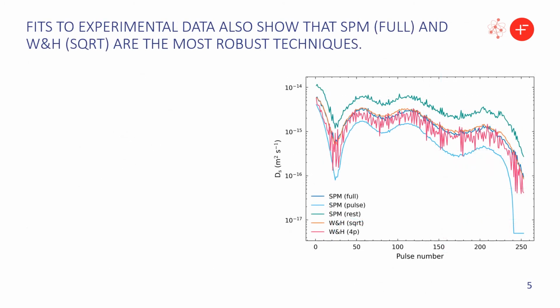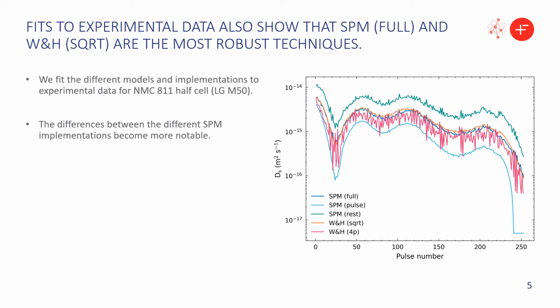So that was the synthetic data, but of course, we want to compare it with experimental data as well. And what we do here is fit the models and the different implementations to experimental data on a half cell using an NMC811 positive electrode from an LG M50 cell. And what we observe first is that the difference between the different implementations of SPM becomes more notable. So in fact, using SPM full is even more strongly recommended because it captures effects both during discharge and relaxation, which is what we want to do. We want to capture everything.